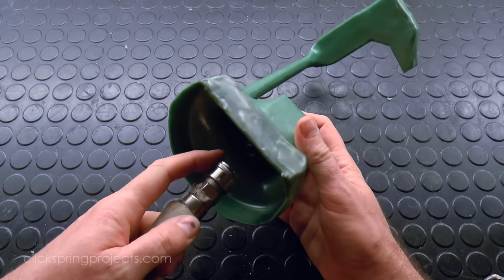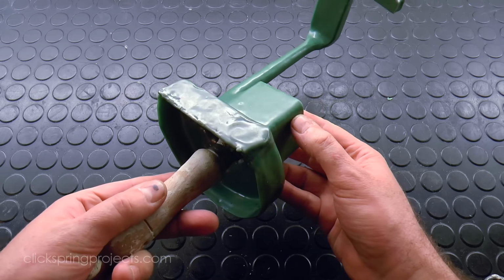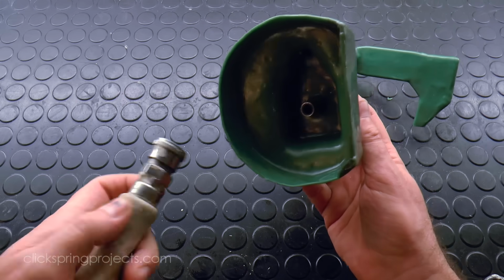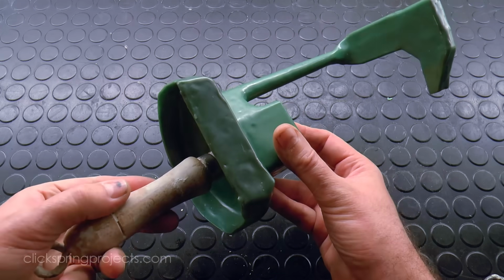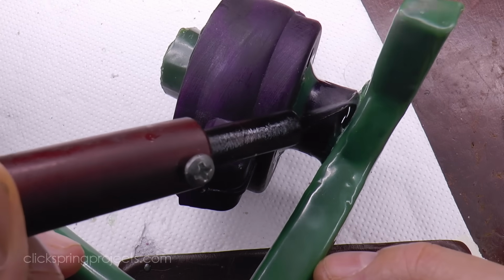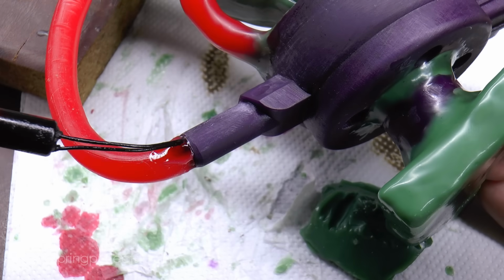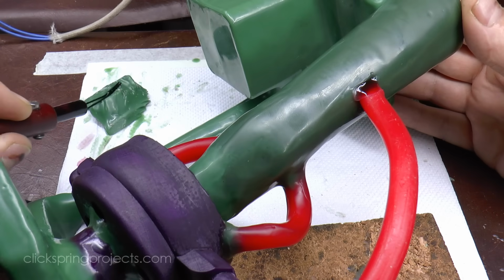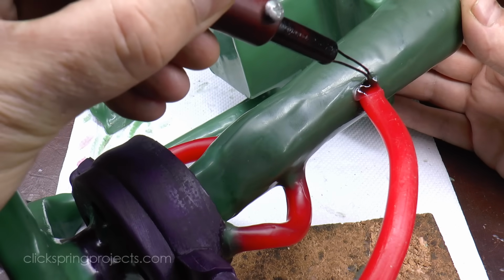The wax pattern, of course, on its own is quite light, but as the ceramic accumulates around it to form the mould, it gains considerable mass. The mould in this video will end up at roughly 3 kilograms by the end of the process. So far, the air fitting arrangement has handled that load without issue.